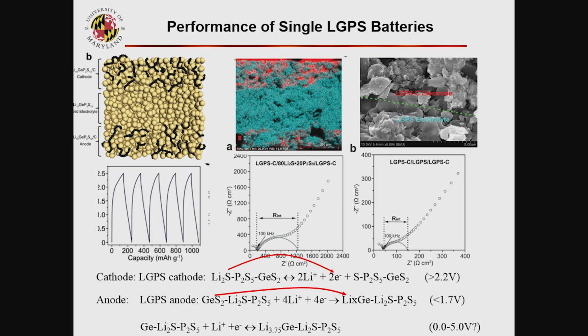So then we build another cell. We use LGPS on the anode cathode, but in the middle electrolyte, we change it to the lithium sulfur and phosphor sulfide. That is the very good electrolytes, 80-20, they can get 10 minus 3 ionic conductivity. That is a 3-layer. In that case, we do have electrolyte interface. And this is the impedance. If we use this electrolyte and the LGPS anode, LGPS cathode, we get interface resistance. This is the resistance. If we use single material, we get 10 times less interface resistance. So that is validate our idea. Interface, we can remove the interface.